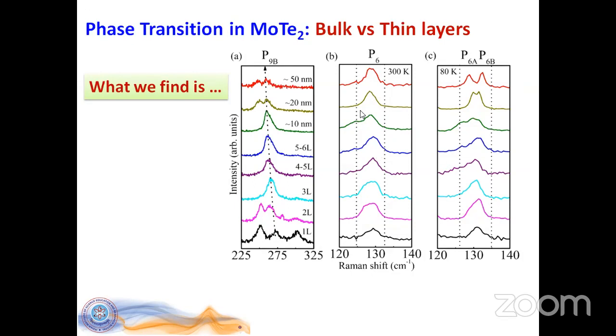Here we're showing at room temperature. The middle panel is the room temperature data, and we can see there is a clear single component over here. Of course, you can see there is a slight broadening over here, which we'll see in the next few slides. And then as we go to the low temperature, which is the minimum temperature in our case, 80 K, you can see the 50 nanometer flake shows very clear splitting, which is the signature of the phase transition. But then 20 nanometer shows still visible splitting of the mode, and then 10 nanometer.